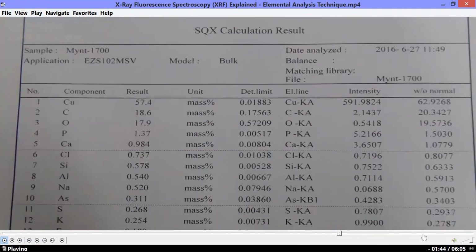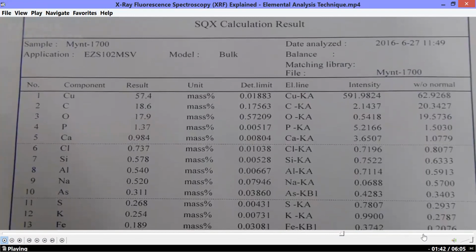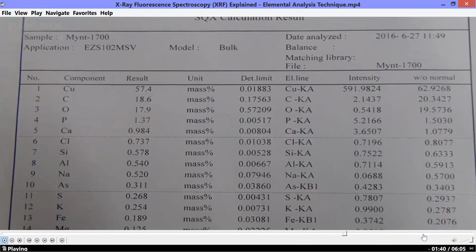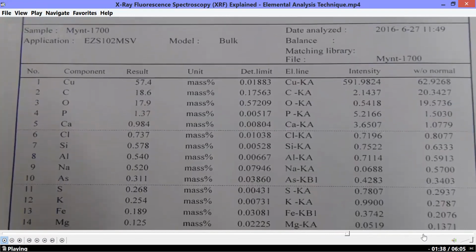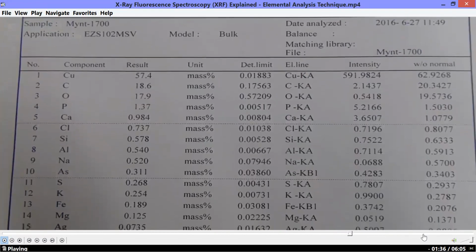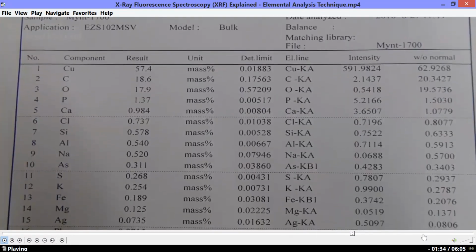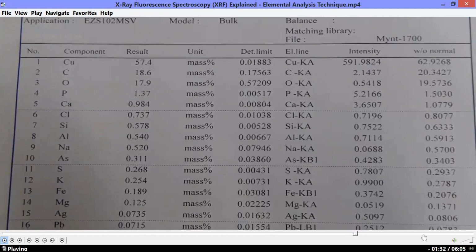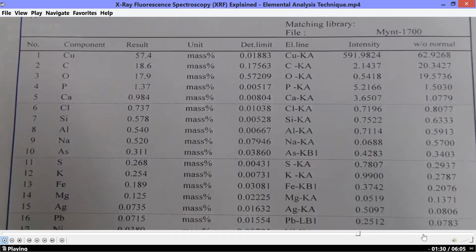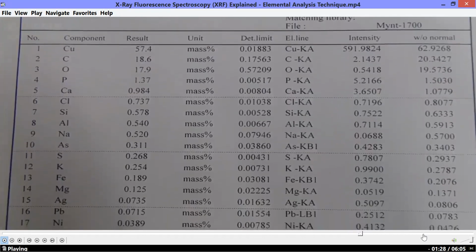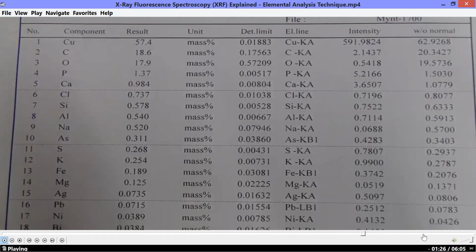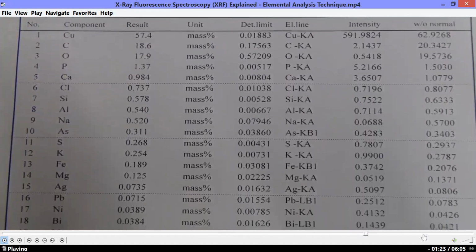Based on that data, it is possible to calculate the elemental composition of the material, and in the case of this sample, we are dealing with a copper coin. The high content of oxygen and carbon originate from the rust layer, while the smaller quantities of other elements, such as arsenic, may indicate that the coin had a colorful history.